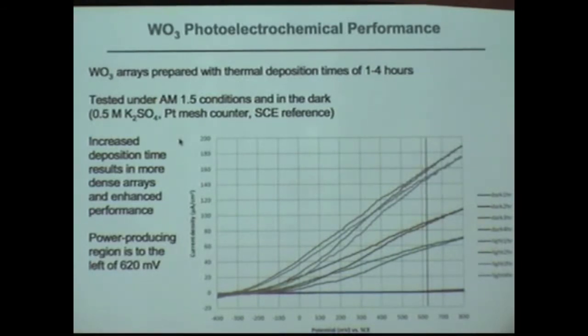Long-term stability of tungsten oxide in water is something that is debatable now, but it's very close to being stable. If we can catalyze the water oxidation just a little bit, maybe with anodic films of cobalt with phosphate, we might be able to bring us that last 9 of stability. So we're trying to see if that works.